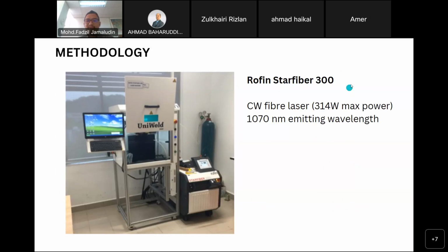So this is the laser that we have used. It's a Rofin Star Fiber 300 with a maximum power of 314 watt, and it has a 1070 nanometer emitting wavelength. It can do continuous mode, meaning that it is very flexible. It can do pulses, it can do continuous, but in our case, because of the welding configuration, we are selecting continuous mode of welding.